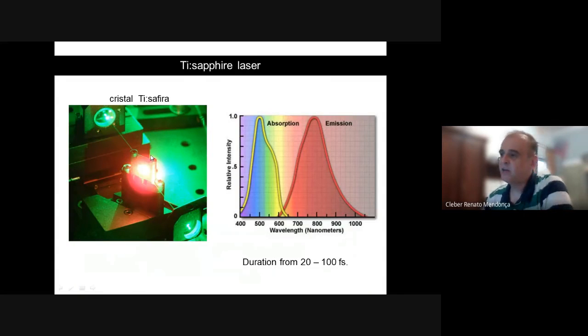I don't know how many of you have seen a femtosecond laser before, but that's a titanium sapphire laser crystal. Here is the titanium sapphire crystal being excited by another laser with green light. As you can see, it's a kind of reddish color. If you look at the spectrum being emitted by the titanium sapphire crystal, which is the active medium for the femtosecond laser, it's very broad. It goes from 600 nanometers all the way to 1000 nanometers.